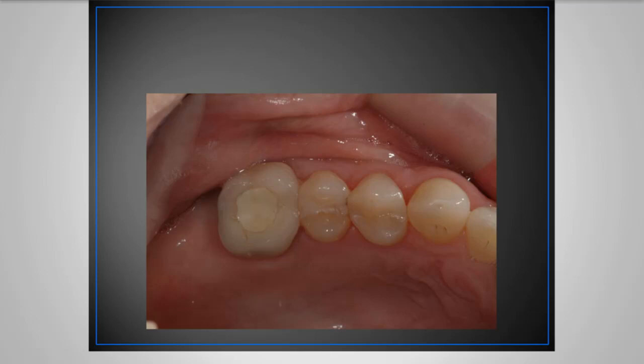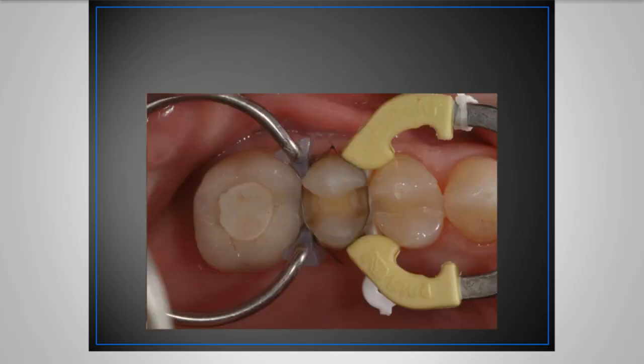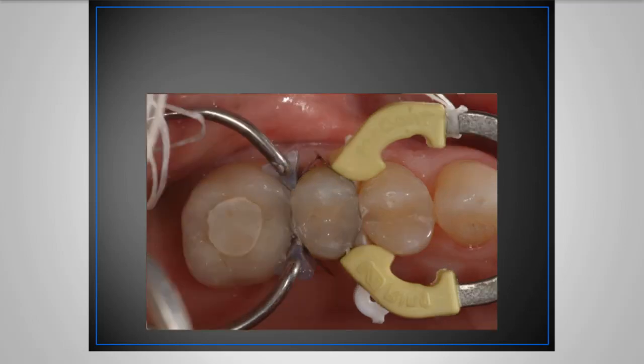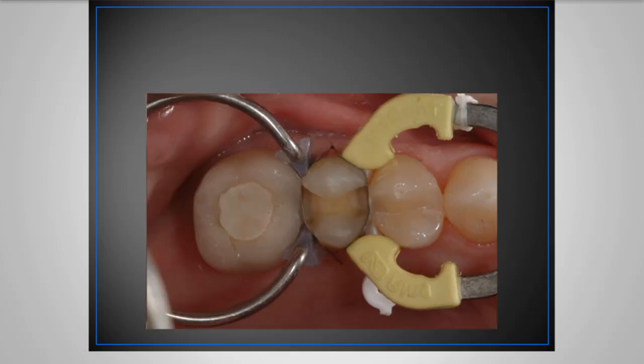So here's an example of a great time in which to use one of these bulk fill composites in which we're replacing the existing composite in this premolar. We're going to place our traditional ring systems. You place your bonding agent and then fill it in entirely with one increment of composite. So in looking at the defect, 4 millimeters or less, and again, I have pretty good pulpal distance, so I like it for this area because really the deepest area is my proximal boxes. So a bulk increment in the proximal box, again, can be very desirable to have one increment. And using the Compules under pressure gives us good adaptation when done properly.